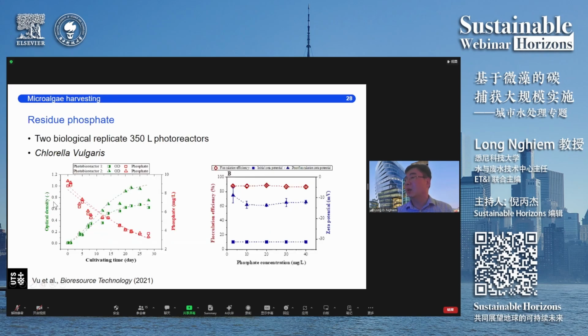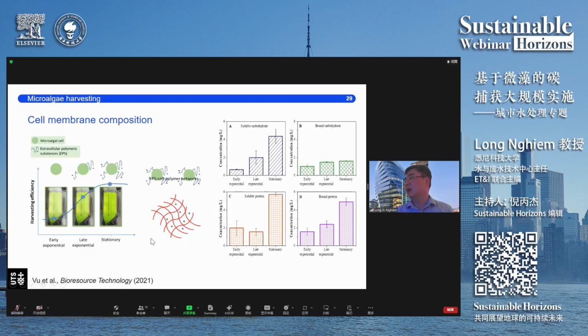When we look at phosphorus residue, what we have done is we add a tiny bit of phosphorus so that we can change the phosphorus content at the end, and we didn't see any impact of phosphorus residue on harvesting efficiency. So we can very much cross out phosphorus. And when we look at the morphology of the microalgae cell, I think that it is probably the main reason why at stationary stage, we always have the highest harvesting efficiency.